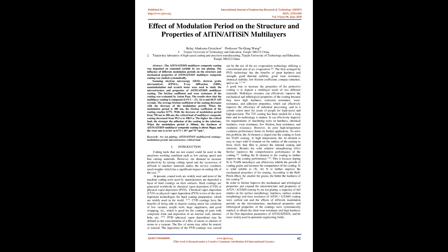Hard coatings are generated worldwide by chemical vapor deposition (CVD) or physical vapor deposition (PVD), two of the most important technologies for hard coating preparation. CVD coatings have the benefits of being able to deposit coating under the condition of low vacuum, simple tools, large suppleness, and good wrapping, which is good for the coating of parts with complex form and deposition of an internal wall, internal hole, etc.